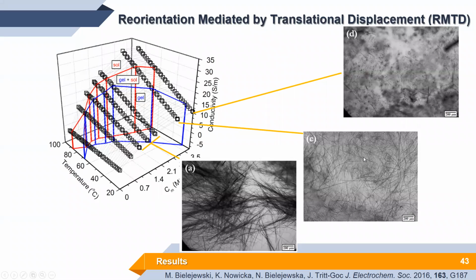is dissolved, it starts to dissolve. So we do not observe the bulk flow, but the internal structure starts to change and basically dissolve the well-defined aggregates. We observed the increase of the self-diffusion coefficient. And actually for the highest, it was already very close to the diffusion coefficient observed for a bulk or pure electrolyte. This is because the fraction of the gel matrix was actually too small to support the gel state, and we have, like almost everywhere, freely diffusing molecules of the solvent.